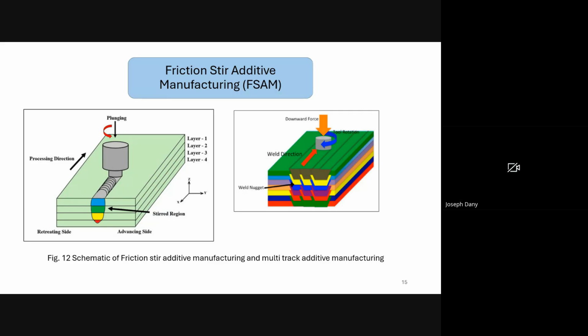Interestingly, studies have shown that 54% of the heat comes from the friction, while the rest is from the deformation. This heat combined with material flow around the tool causes the plates to consolidate at the back of the tool, forming a solid joint. The final thickness of the part depends on various factors, something like the thickness of each sheet, how the sheets are arranged, the total number of sheets, the dimensions of the tool pin, and the plunge depth of the tool. Also, the tool position during welding directly affects both the microstructural features and overall geometry of the part.